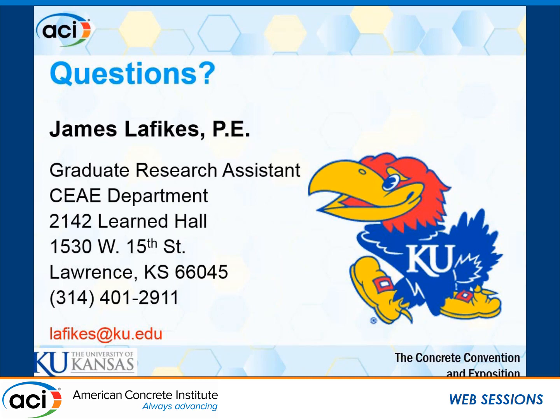We do have time for 1 or 2 questions. Okay, your research is very commendable, but I don't want this group to walk away with the impression that slag is necessarily going to reduce the incidence of settlement cracking. You used 30% slag, which is about the bare minimum that would be recognized for use in the industry. Anything under 30% is nothing. Had you used 50% or 60% slag, recognizing that slag bleeds longer and is a slower bleeder, you may not see the same results. So I just don't want this group to walk away with the impression that simply putting slag into the concrete is going to reduce your incidence of settlement cracking.